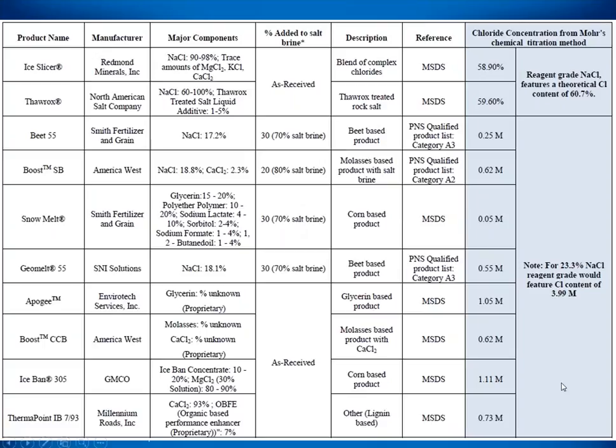So essentially we're just measuring the chloride concentration of the agro-based product that's then mixed with the salt brine. And for the category C products received from the vendor, you have the molar concentration here, and you can see for some of these they have a much higher molar concentration. Again, for some of these, due to proprietary protection, the concentration of the various components was unknown. This test method is not fault-proof. There are some elements that are present that can interfere with the test method. It's not 100% accurate, but this is what we were able to report from the testing that we conducted. I hope that answers your question, Clay.